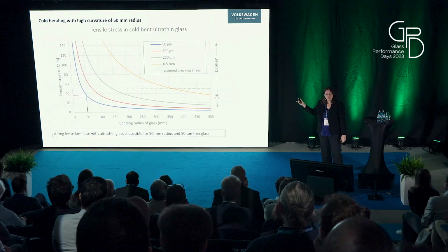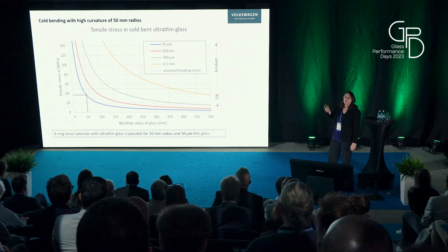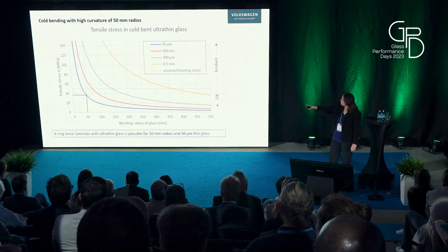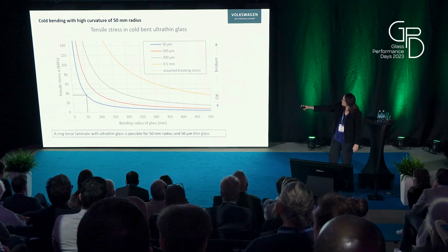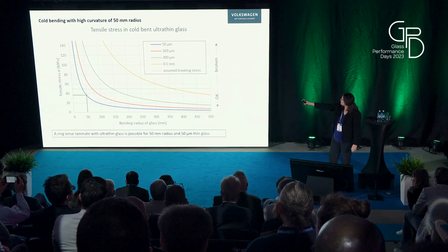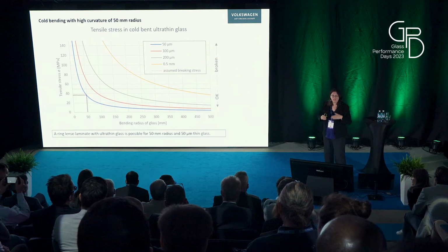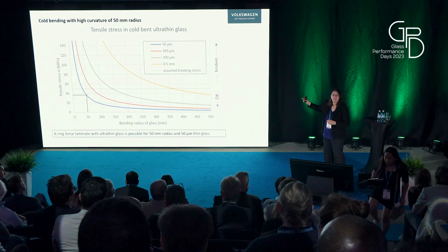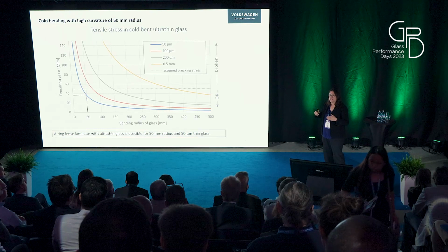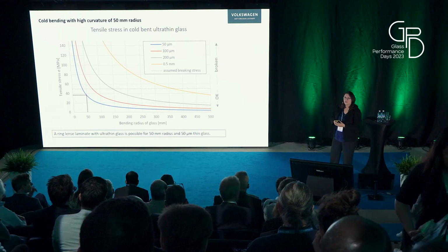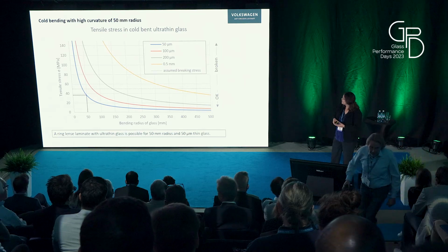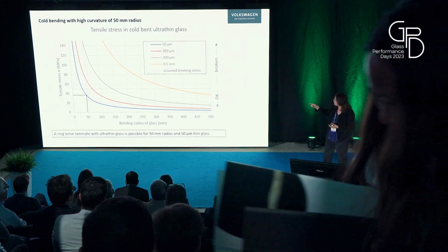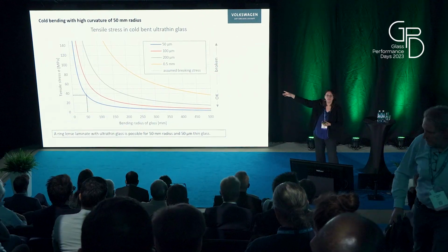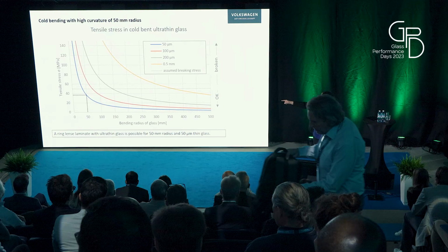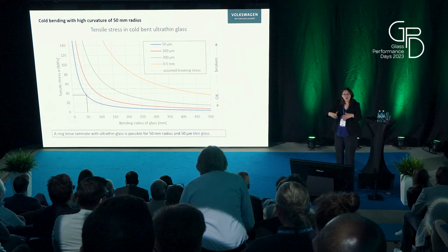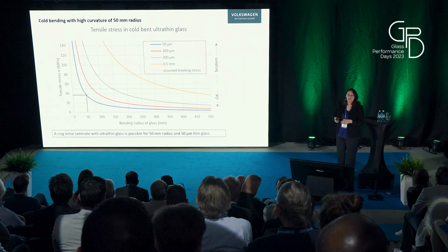And talking about the ring lens we just seen, you should choose 50 micrometer for that, because if you are following the line of 50 millimeter radius, you can assume maybe 50 megapascal breaking point here. That can depend heavily on the quality of glass edge and surface. But Nippon Electric Glass gave that range approximately, so I took it here as well. And if you just follow it, for example, for a 100 micrometer sheet of glass, which would be the orange line, then you see you're above that breaking point already. So for these small bending radius, you have to be as thin as 50 micrometer.